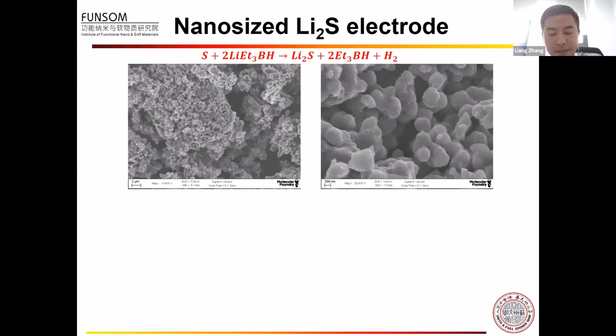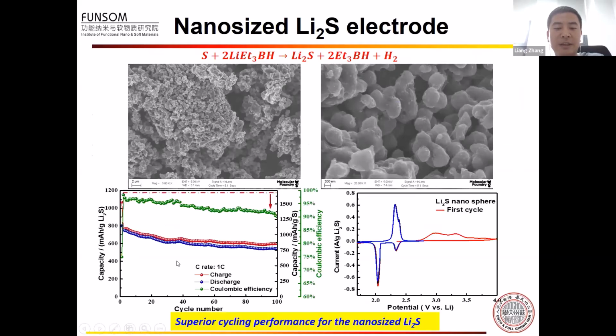Therefore, we use the in-situ operando XAS to investigate the reaction mechanism of the lithium sulfide electrode. Here we use a very simple chemical method to synthesize nano-sized lithium sulfide materials. We can see the shape is round, with an average particle size of around 500 nanometers. The cycling performance is not pretty good, but it's okay. After 100 cycles, the capacity is still more than 800 milliampere hour per gram.